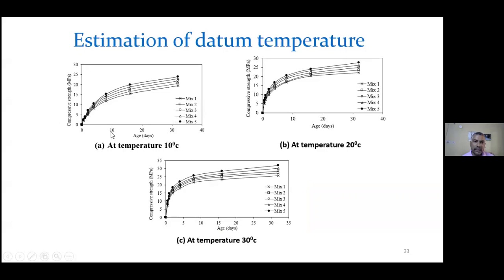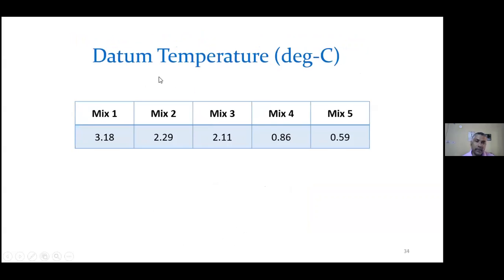And you see at 10 degrees, you have 5 mixes. When it is cured at 10 degree temperature, this is how the compressive strength versus age data progressed, and this is at 20 degrees, the same figure at 20 degrees centigrade and at 30 degrees centigrade. Once you have this data, we find out the datum temperature by the calculation procedure. You must remember these are actually averages of 3 specimens. Please note that. So we found the datum temperature for each of the 5 mixes, where T naught in degrees centigrade is the datum temperature. That was one precondition for our procedure for this maturity method.